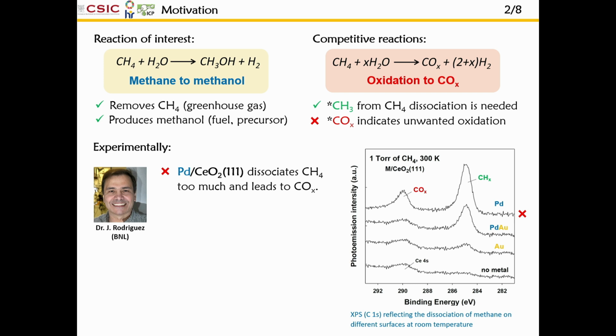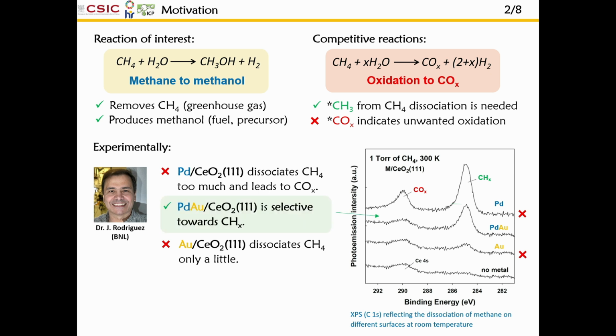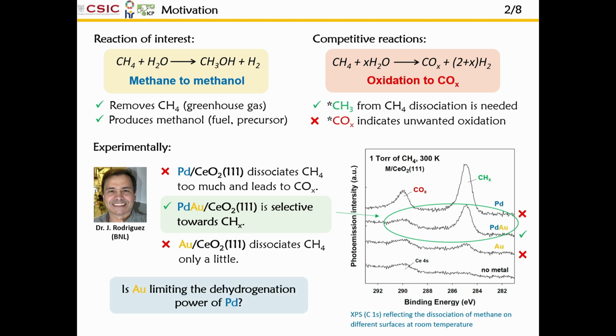So when you have palladium nanoparticles on ceria, then you see both peaks, so it means you do not have selectivity. It is too active, but it doesn't have the selectivity that you want to methanol. If you use gold nanoparticles on ceria, you have no activity whatsoever. But if you mix the two, you can find the specific ratios for which it is selective to methanol. And the amount of palladium is relatively low compared to gold. So the idea is that gold is somehow limiting the dehydrogenation power of palladium.